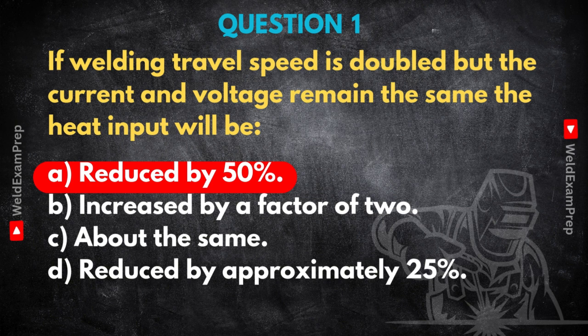Why so critical? Because heat input controls so much. Too much heat, you risk things like coarse grains in the HAZ, lower toughness, maybe more distortion. Too little heat, you could get lack of fusion, not enough penetration. So it's a balance. A really crucial balance. It directly impacts the weld's properties, its strength, its ability to handle stress. An inspector needs to know this relationship inside out. Okay, that makes perfect sense. So controlling speed is key to controlling heat.